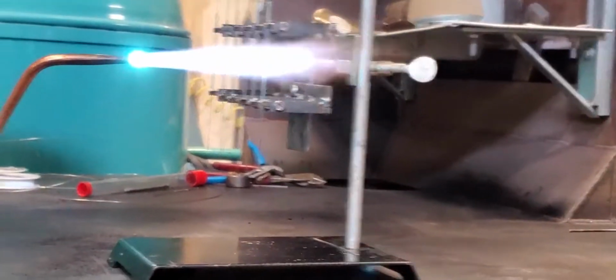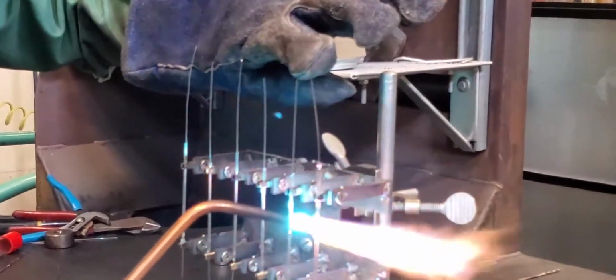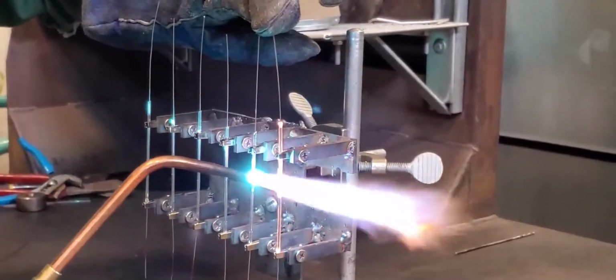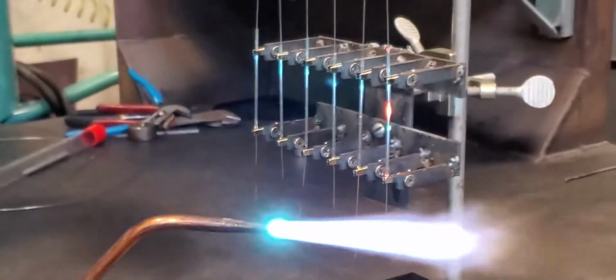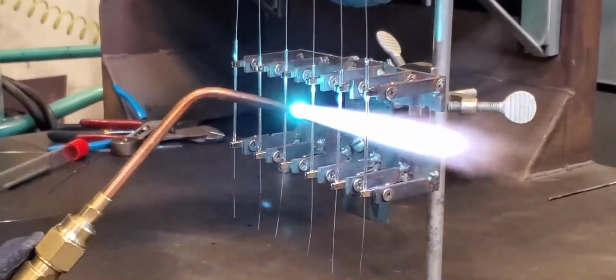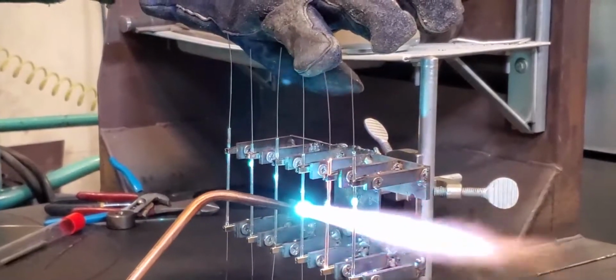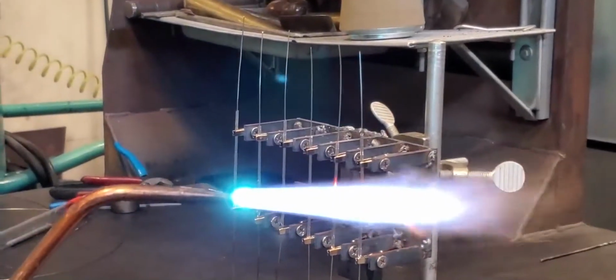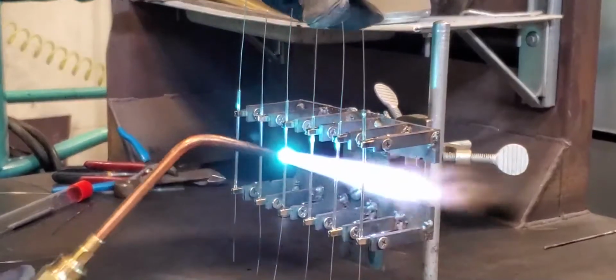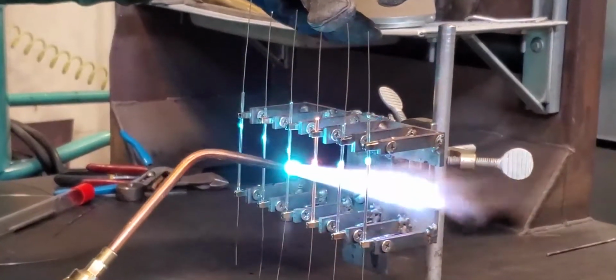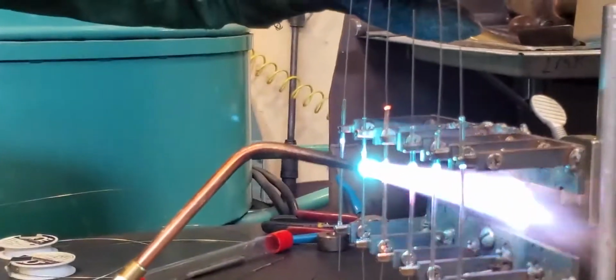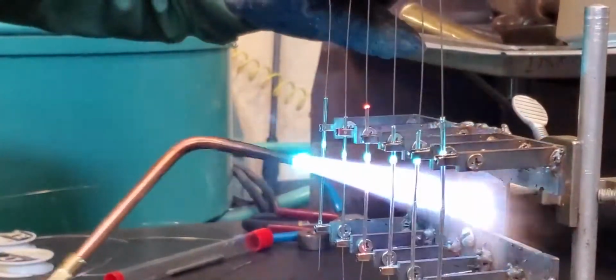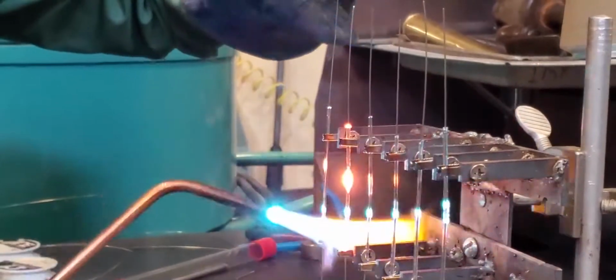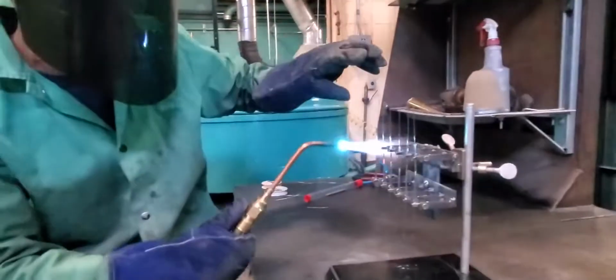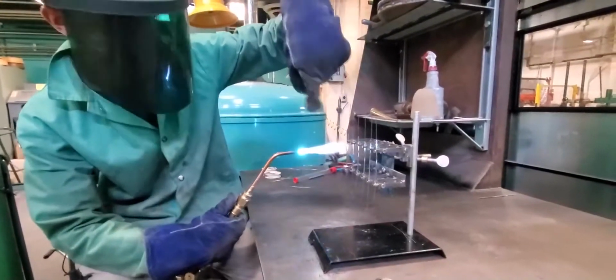Now the idea is apply a slight amount of pressure while heating the junction up. As soon as it's molten, just pull away. Like pull the torch away and then release pressure. That way, you do a little bit up and down to slightly anneal the wire since it has been cold worked, that helps. Otherwise, it can start to bend when everything gets molten and soft.